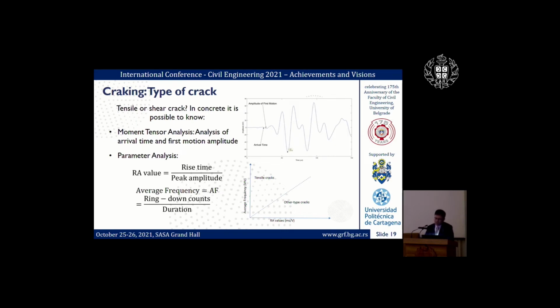And then you can use another kind of analysis that is called parameter analysis, which is based on 2 parameters that are defined that way. The rise time divided by the peak amplitude, and the average frequency, which is the counts that you have in your hit, what is the number of crosses over the threshold, divided by the duration of your hit. It's a way to measure the frequency, not very academic, but it can give you an idea of the frequency of your wave, and it is used to classify your crack.